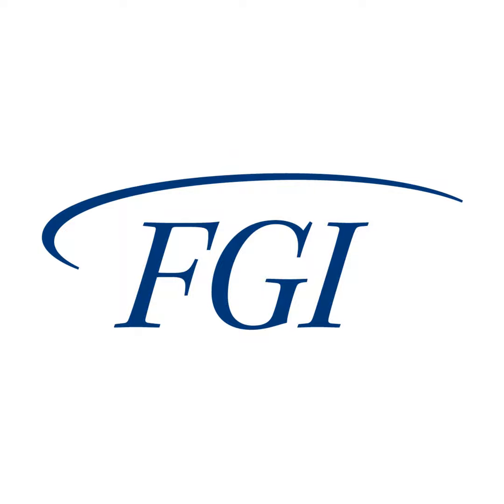In this case, again, we see that HPOIT was very little benefit for the immersed geomembrane. Again, I want to say that doesn't mean it's not important for other reasons, such as UV exposure. But when we immerse it, for at least these cases, it made no significant difference. So how long the geomembrane lasts is going to depend on the polymer.